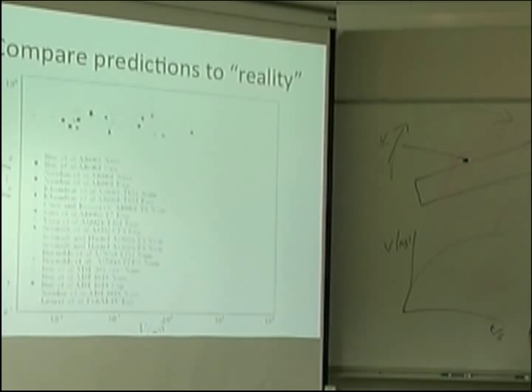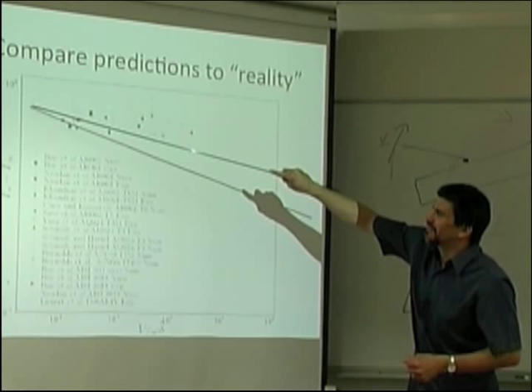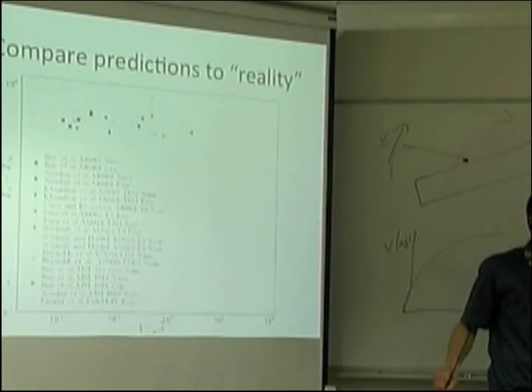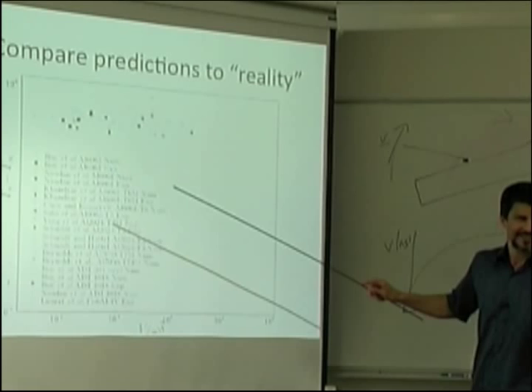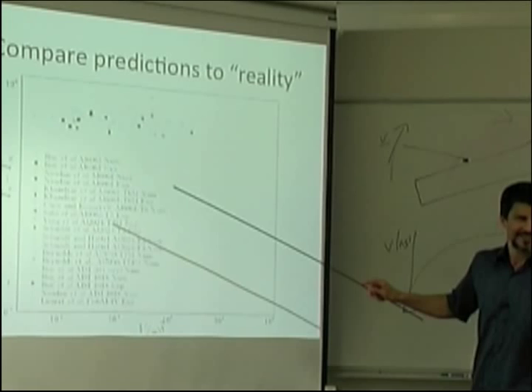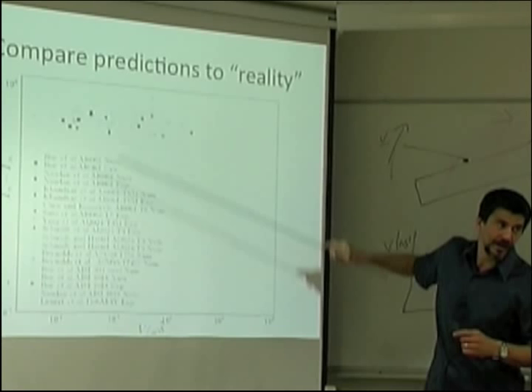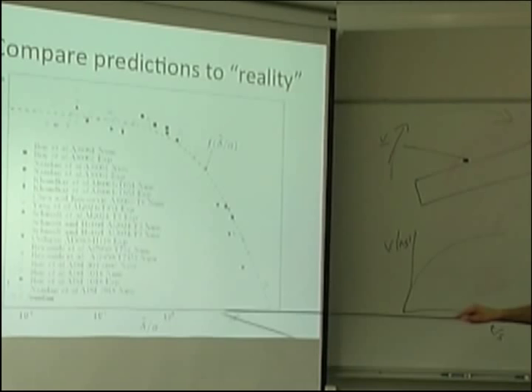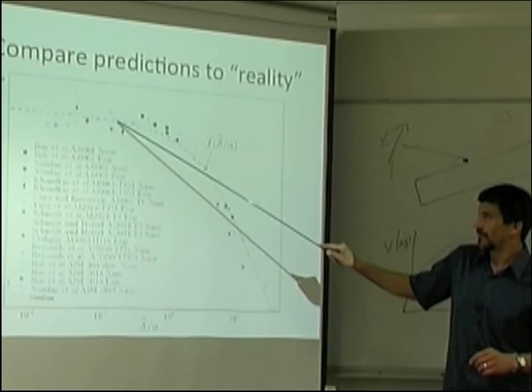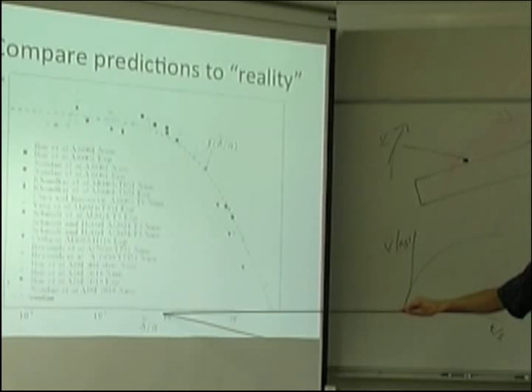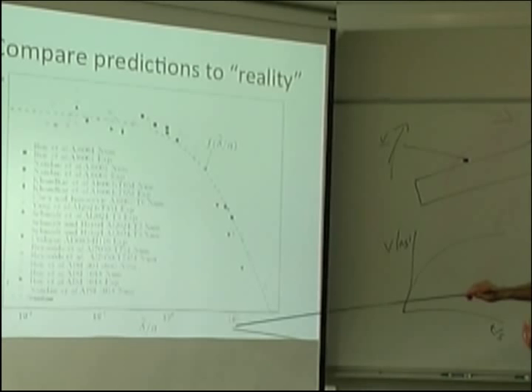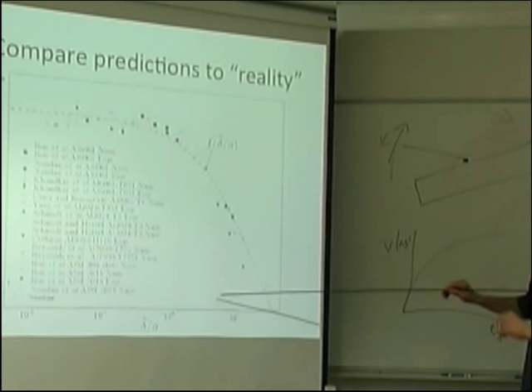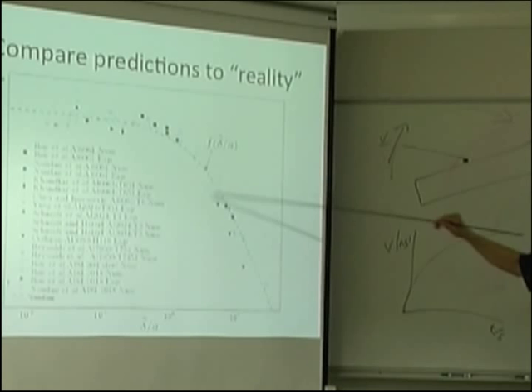And when this number is big, my model is not good anymore. Or if it is good, it's by coincidence. But I cannot say anything. So this is this other region. What do you get to see? That for lots of practical cases, my hypothesis was true. The hypothesis. So my model does apply for all these practical cases. And when it applies, I get it more or less right. It also says that there are a bunch of other cases for which my hypothesis did not really apply. In this case, you could say that advection and conduction are more or less even. So my model doesn't really apply. But we include it here. And we see it's still kind of working, kind of magic. I'm happy that it does. So I cannot explain this based on my model. But I like it and I'm going to keep it there. What do you get to see here too? Look. Some points are for 6061 aluminum. Some are for other type of aluminum alloys. Look at this. 304 steel. 1018 carbon steel. And they all fall more or less on the same line. I'm going to show you another one. So here is when I said flow from rotation dominates over flow from translation. And it's more or less the same. And here you get to see even titanium. We have some titanium there.